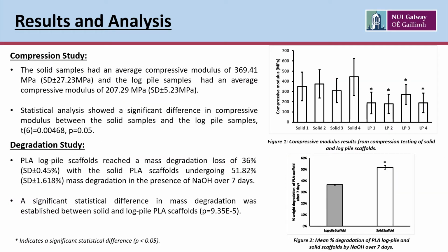Here are the results and analysis from our experiment on the log pile scaffold. The results from the compression study show a significant difference for the compressive modulus between the solid and log pile samples. From the degradation study, results revealed that the solid PLA scaffold degrades far more than the log pile scaffold. There is also a significant statistical difference established in mass degradation between solid and log pile PLA scaffolds.